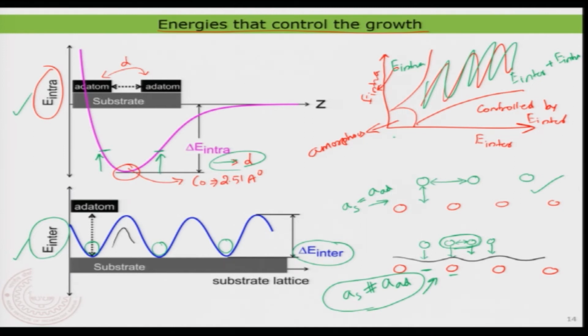And now here at this low regime, none of the energies are contributing enough so that the ad atoms can adsorb and then form a crystalline surface. So what happens in that case is the formation of an amorphous layer at that site. So that is the general thing. Just keep this in mind. You need to exercise it a little further for your own understanding, and now you will see a few examples, and then you can understand this a little better.